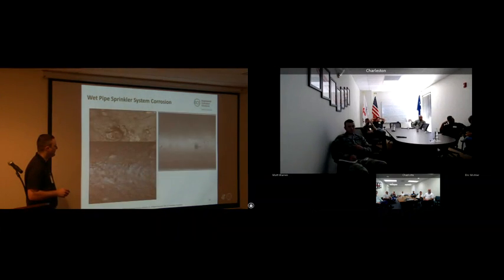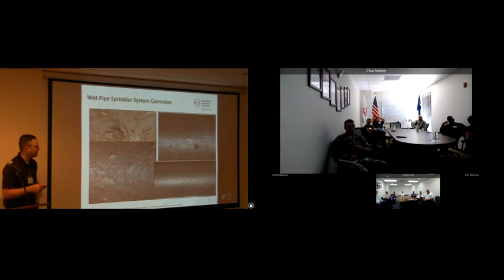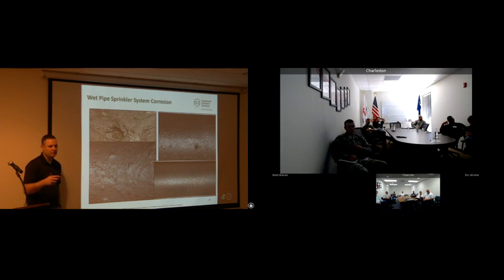So what those pipes look like when we clean them up, this is what they look like. In the upper left-hand corner, you can see how smooth and aggressive that hole is, that metal loss is relative to the rest of the pipe. That is classic oxygen. If you move over to the top right picture, you can see the through-the-wall failure. You can see how deep and smooth that pit is, what the metal loss is when you look at the surrounding area. That's classic oxygen corrosion.